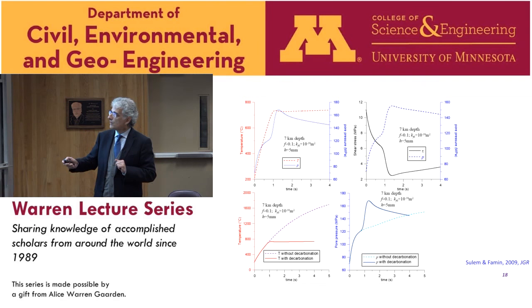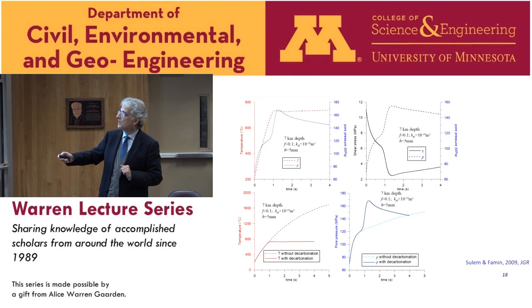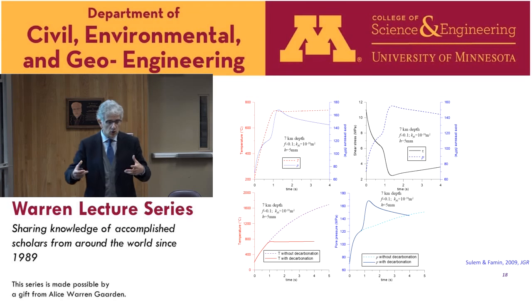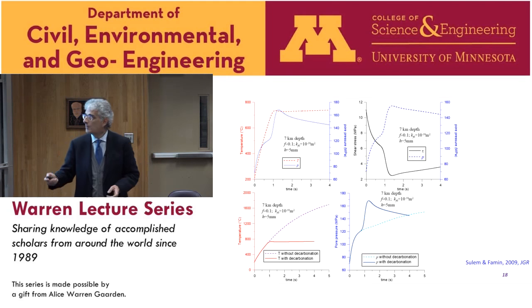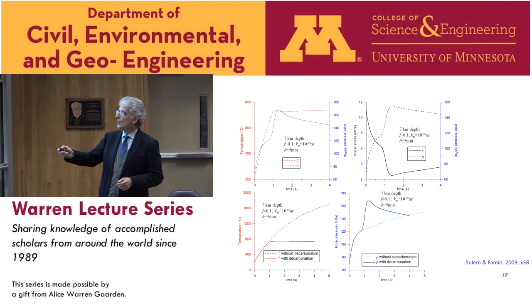We have the temperature rise here. After 1 second, it reaches the critical temperature for which the decomposition of carbonate is possible. And you see that after that, the temperature stays almost on a plateau. For the pore fluid, we have the first phase, which is the thermal pressurization of the pore fluid. Then when the reaction is triggered, we have an acceleration of the pore fluid pressure increase. And because it is in competition with the increase of the porosity and of the permeability, it reaches a maximum, a peak, and then decreases.